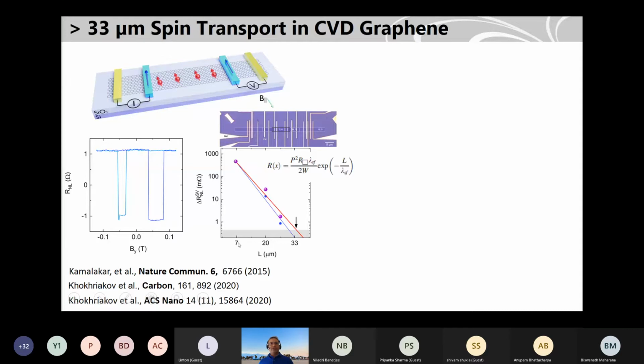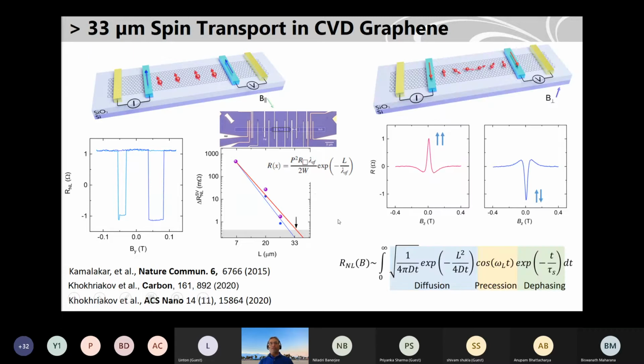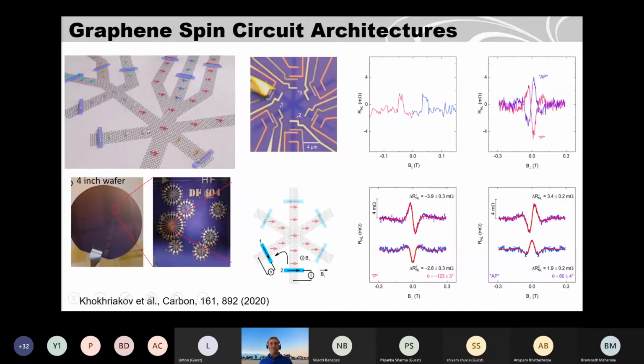How do you study the spin transport? You can make devices of different channel lengths between the source and drain. Then you find the magnitude of the spin signal and plot it. It should decay exponentially according to the spin diffusion theory. You have the resistance change, and this is the polarization of contacts 1 and 2, which is squared here. And this is the spin diffusion length, and the signal decays exponentially with length. If you fit it, you find the spin diffusion length, and it's around 7 micrometers at room temperature. You can also do these Hanle experiments as I showed you. This is for very long spin transport devices.